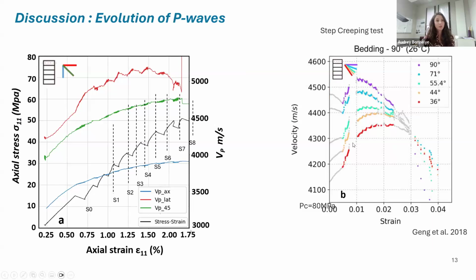And actually, we observed that previously while we were doing some step creep experiments during the PhD of Geng in 2018. The behavior that we see is very similar to something that could be done under triaxial conditions and some evolutions that we have observed previously. Also, if we correct everything and represent now the velocities as a function of the strain, we see a classical behavior, meaning that we can observe the compaction, and at some point we start to observe the decrease when we leave the linearity of the stress-strain curve.